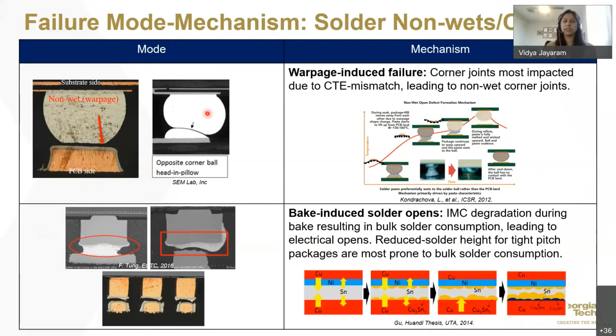And in some cases, you have the bump touching the pad, but it hasn't made a good enough contact to actually form a joint. So that can also lead to non-wet.